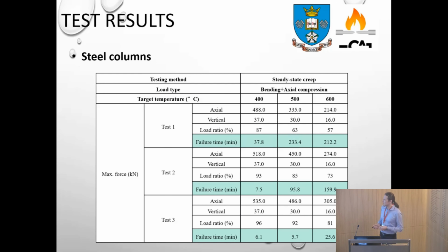As far as the results go, we did a number of tests at 400, 500, and 600 degrees. So we're talking about steady state creep tests. The load ratio, the phi that I mentioned earlier, is defined in this line here for prescribed temperatures from 400 to 600 degrees.